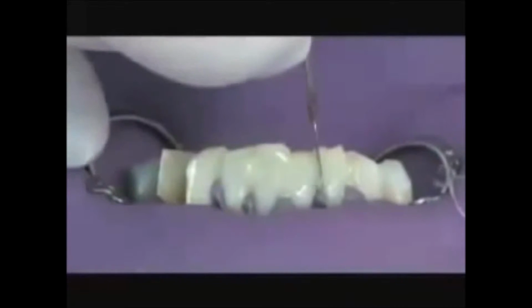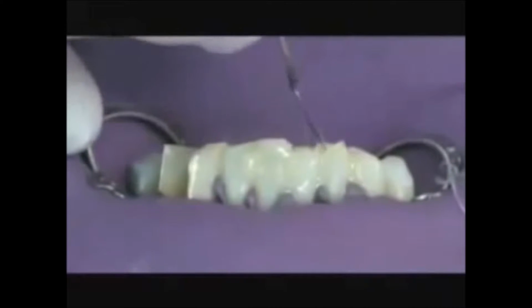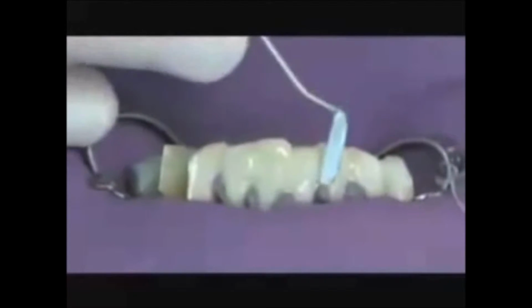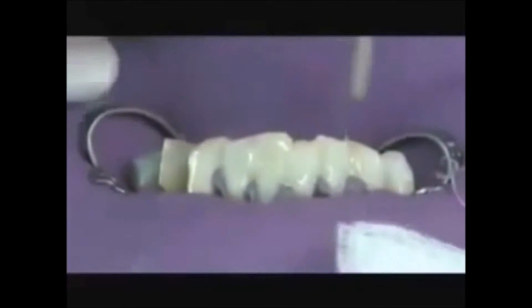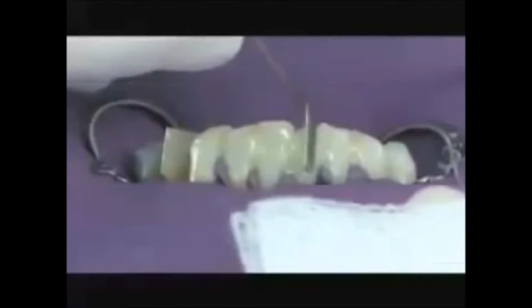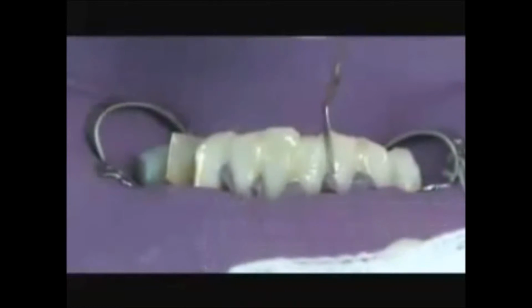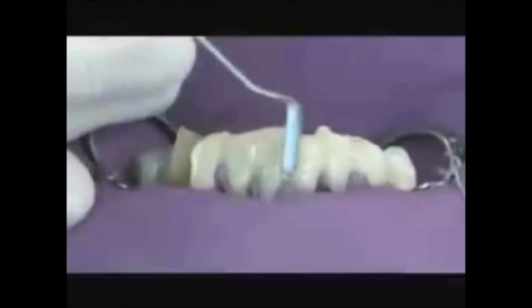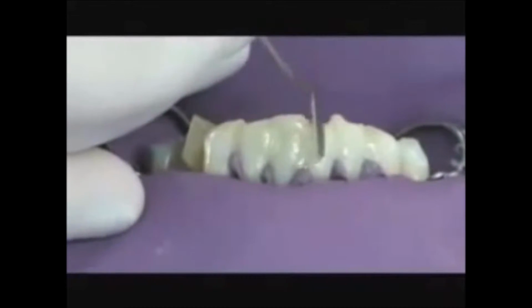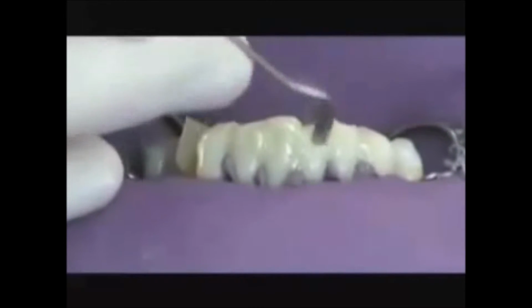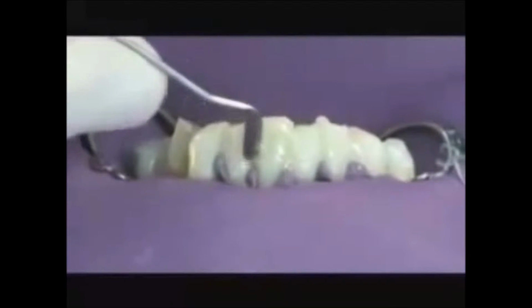This step is really very critical so that the teeth don't shift and move when we place the splint on the lingual surface. If we don't place this facial composite, the teeth will shift and torque, the splint will fracture and prematurely fail. Also, by sealing these interproximal embrasures, we're not concerned about interproximal decay forming in these areas. We make sure that the enamel's covered. We'll be finishing these areas later, but we try to remove as much excess as we can on these surfaces.